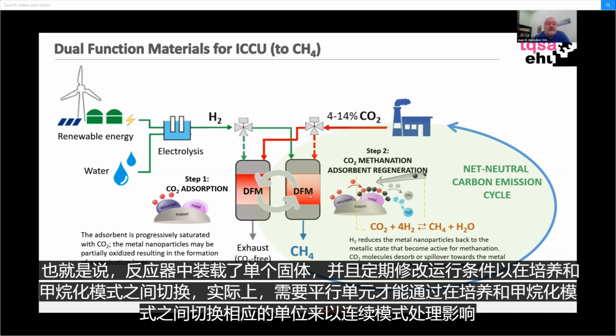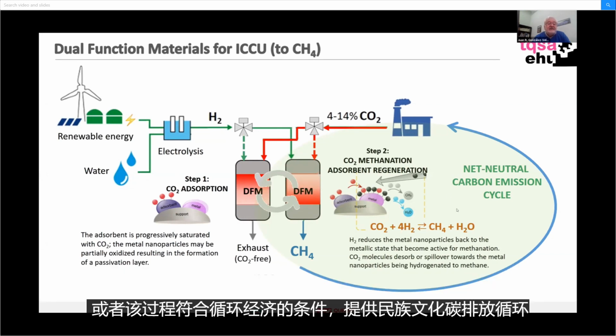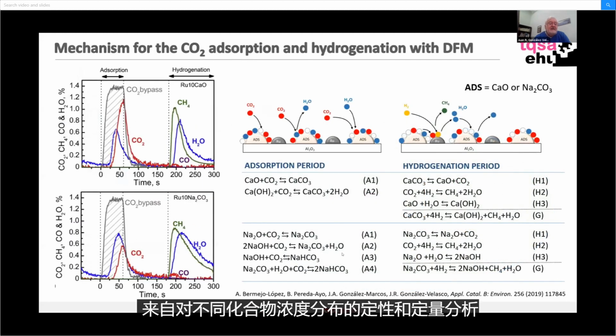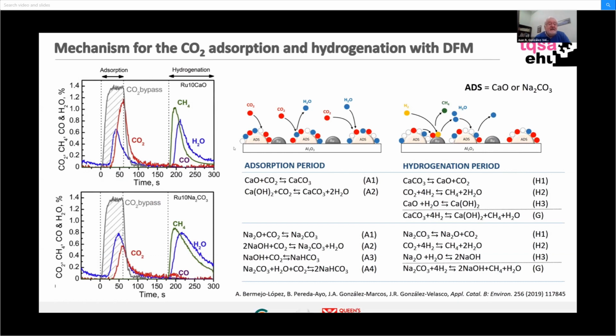Practically speaking, one would need two parallel units to be able to treat effluents in a continuous mode by switching the respective units between the capture and methanation modes. The process meets the condition of circular economy, providing a net neutral carbon emission cycle. From qualitative and quantitative analysis of different compound concentration profiles, together with FTIR analysis for identifying different compounds, we have proposed a complete reaction scheme describing CO2 adsorption and hydrogenation, which is represented in this slide for ruthenium catalyst with calcium and also sodium adsorbents.